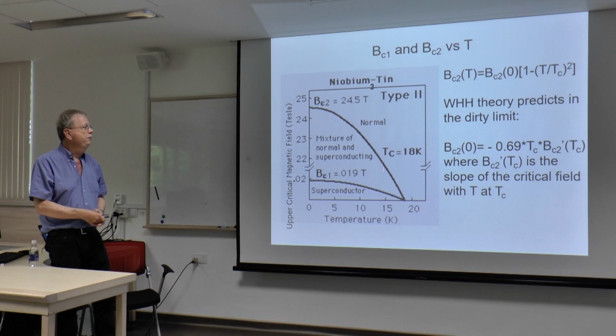Here are the critical fields versus temperature for niobium 3 tin. It's obviously a type 2 superconductor because here is, depending on whether you're talking in the superconductor or outside the superconductor, here is HC1, rather low number. Notice that this is lower than it is in niobium, for example. And here is the upper critical field, 24.5 Tesla.